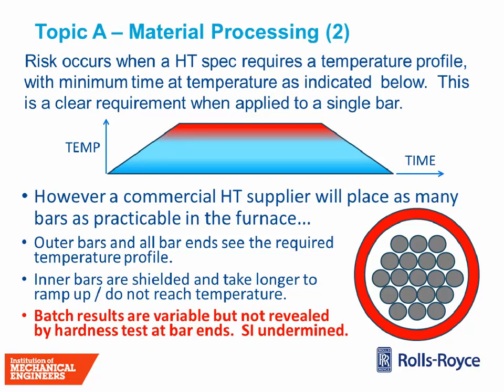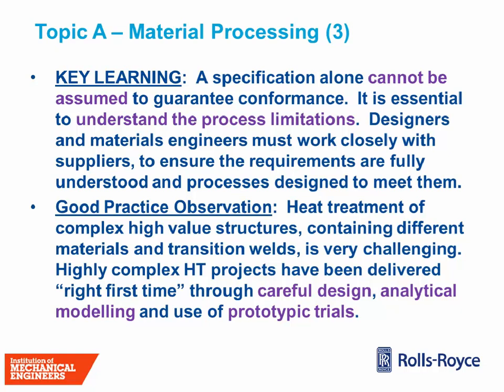So in this example, where the bars are tightly packed together, the outer bars will see the temperature profile shown, the ends of the bars will see that profile, but the inner bars and the central sections of the inner bars are shielded by the material around them, and take longer to ramp up. They either might not reach the peak temperature required, or they might not stay at temperature for the required amount of time. And if your quality test is to hardness test the ends of the bars, that failure to get all of the material up to the same temperature will not be revealed, because the ends of the bars will meet specification. So if you don't understand that and don't do something to manage it, structural integrity could be undermined. You could have significant variation in microstructure, significant variation in properties, and not achieve what the design has intended.